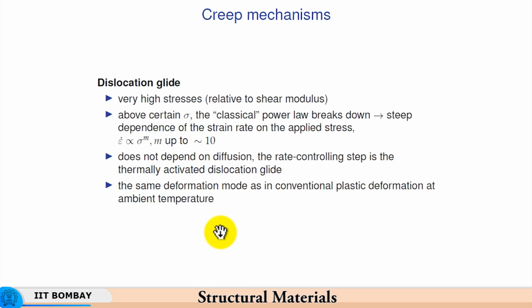Now, dislocation glide alone is something that will need much higher stress, because now you are not talking about dislocation climb or something like that. So, you need very high stresses related to the shear modulus. Above a certain stress, the steep dependence of strain rate on the applied stress comes into play, and so sometimes the sensitivity of strain rate to the stress increases significantly to the power of 10. So, the classical power law breaks down, meaning the dependency of up to say 4.5 to 5 which we saw earlier.